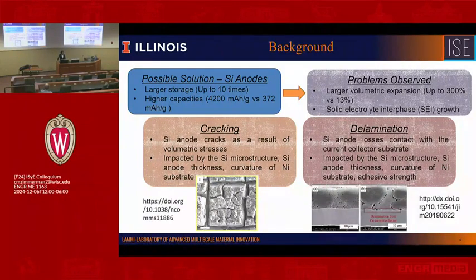Such a huge improvement in performance is due to the very special, unique intercalating, alloying mechanism. So we can incorporate more lithium ions into the silicon crystal structure. But such a unique lithiation process also leads to problems, because by bringing in more ions, they induce a large volume change in the electrode.